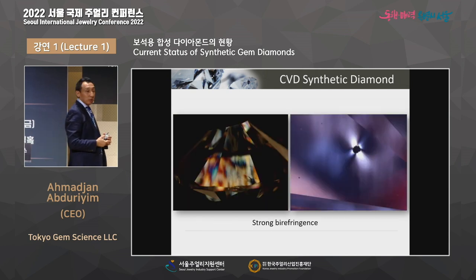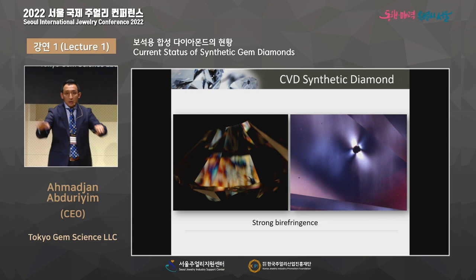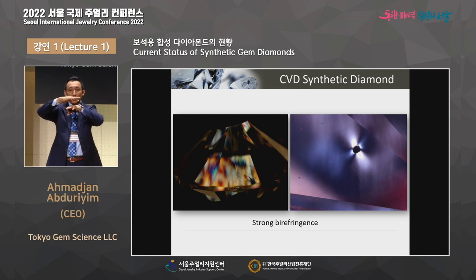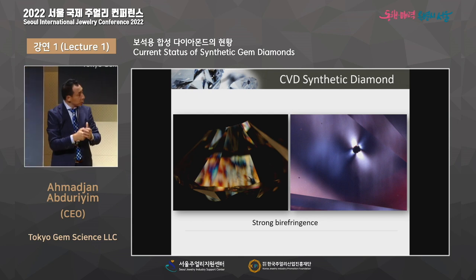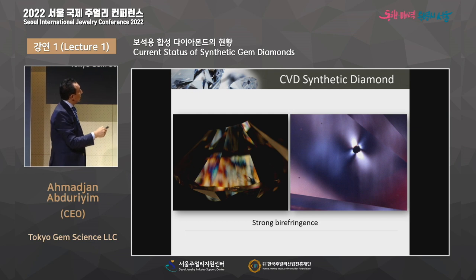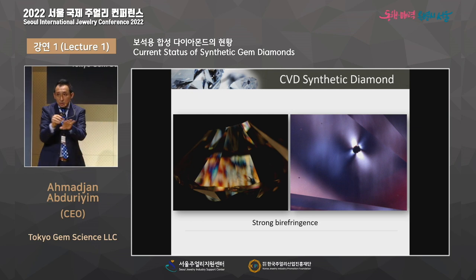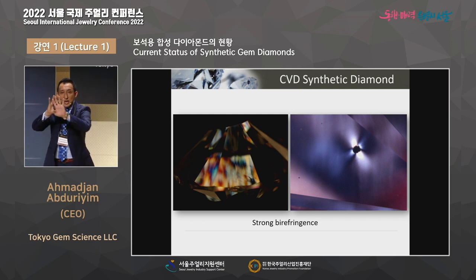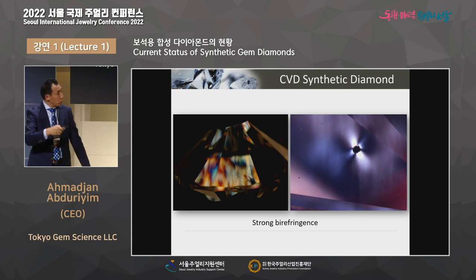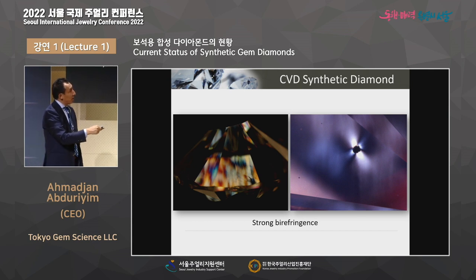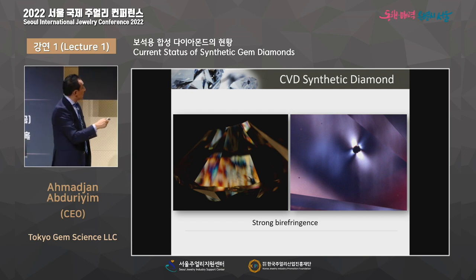And when you look at this diamond under the polariscope, with different light, you will see a bunch of birefringence like this. It's because they grow so fast, they have a distortion. So you will see this kind of very strong birefringence. So the polariscope helps you to see this; this may be a CVD diamond. One minute, you have to stop that as well.